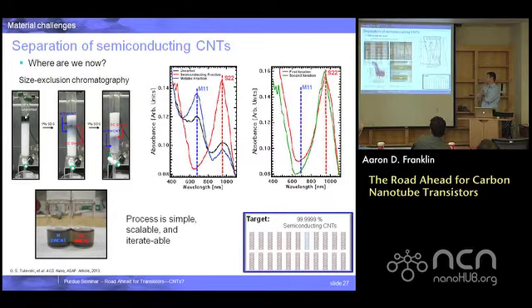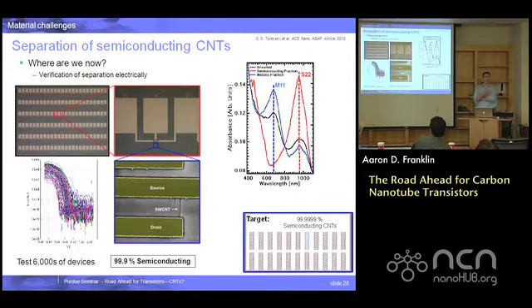But as I said, most important was determining what the actual purity is. And this is not a final slam dunk solution. It just gives us really one or two more nines. And that is, make devices out of them. Actually, build near 10,000 transistors and put them through a semi-automated probe station, let them run for a day or so, and then determine how many of them were metallic. And based upon that, give ourselves a more comfortable figure.